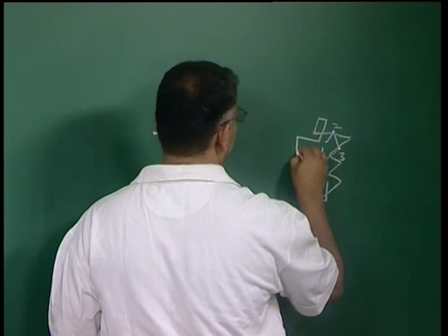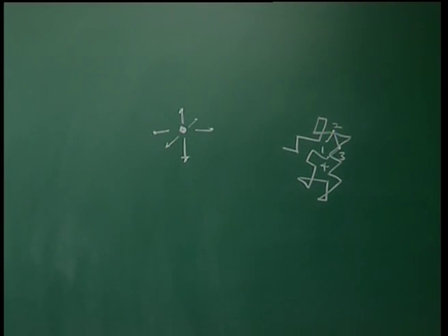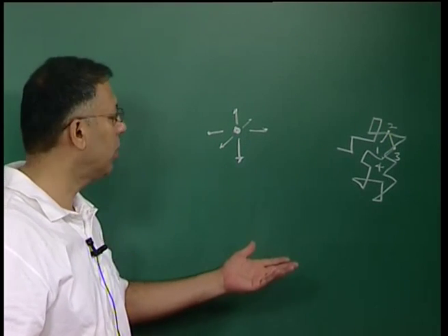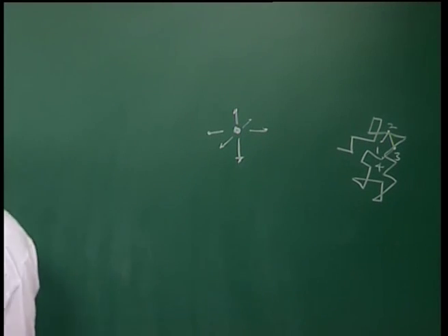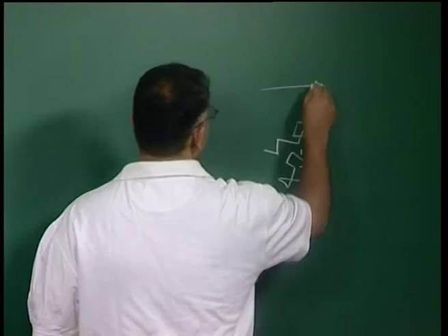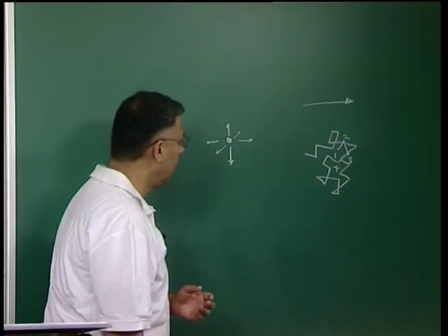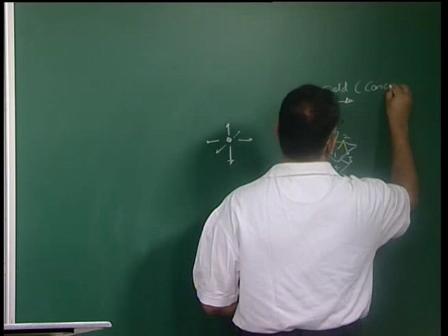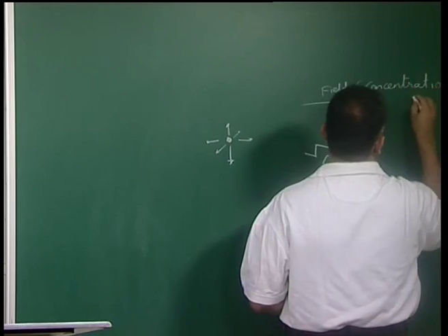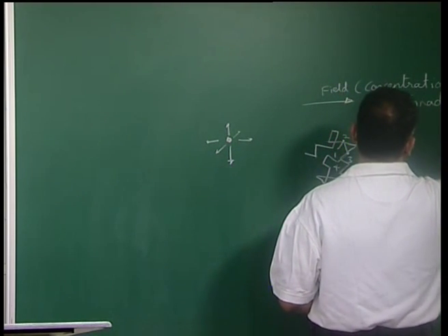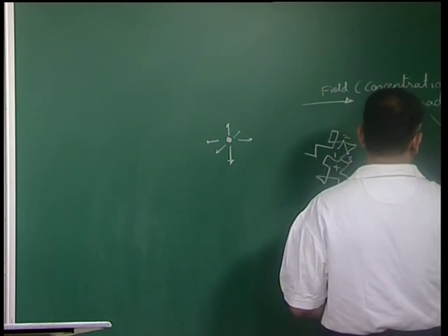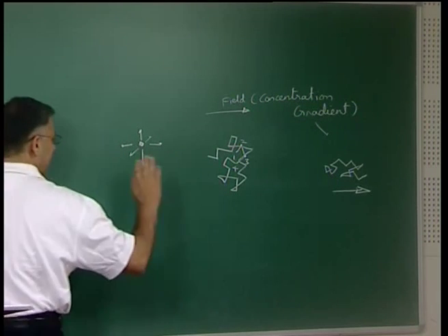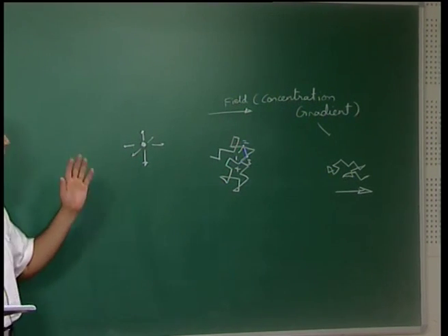This species keeps on jumping. In the absence of a concentration gradient there is no net flow — the atom essentially remains in its vicinity and keeps on jumping, and if you track the average position over time, it is as though the atom remains in the same place. But if there is a concentration gradient — which can be a concentration gradient, an electric field, or driven by stress — then these random jumps lead to net flow of matter down the concentration gradient, or more precisely, down the chemical potential gradient.